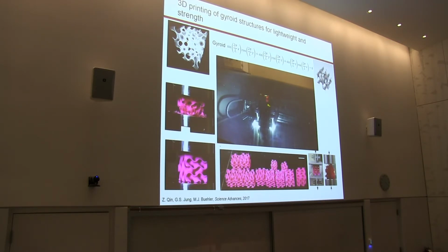So pay attention here. It's still compressing, but then suddenly it explodes because it breaks a lot of the surfaces and the bonds between those pieces. So they have very different mechanical processes for those different designs. This one is more deformable and breaks gradually, but this one is less deformable, very rigid, but can break instantaneously once it reaches a certain level.